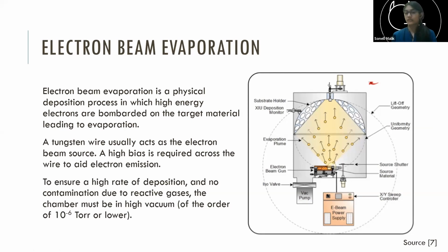And these electrons are high energy. So when they strike and dissipate their energy at the target material at a particular place, it heats up the material, which causes evaporation. So it is kind of like thermal evaporation, but in this case, there is very localized heating. You're not heating up everything. You're not even heating the container in which your material is kept.